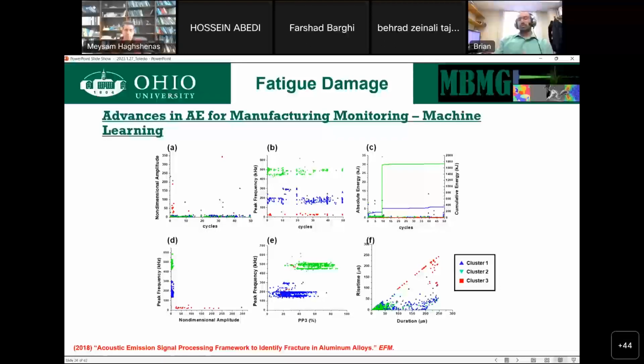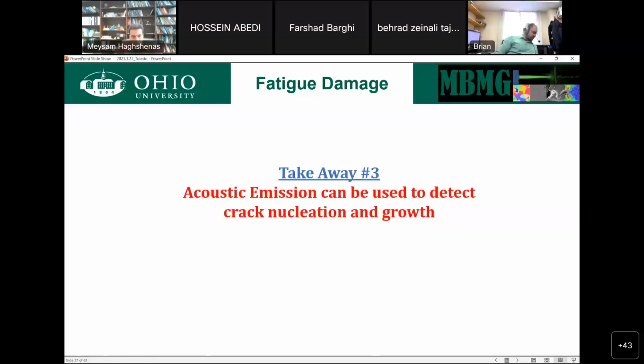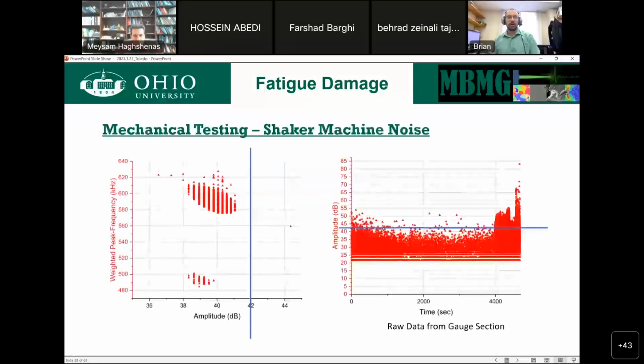But the power of machine learning is it gives us the ability to see these trends, which we can then take and try to leverage against what we're trying to understand, which is how the material responds to load. So, acoustic emission can be used to detect crack nucleation and growth. We saw that a little bit before. We've seen that when we originally acquired the data, trying to go hunt for where the crack is. We've seen it when we're starting to leverage machine learning to see how the trends are evolving. But we can do that across other modalities.